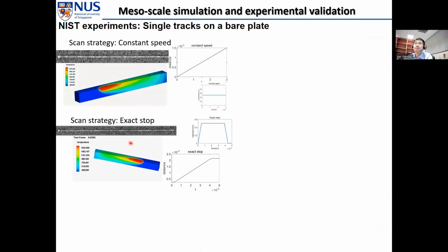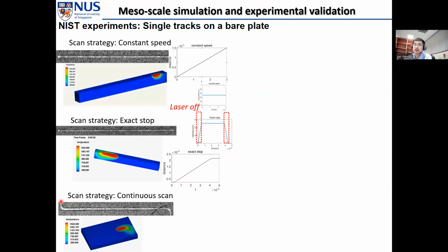So to scan a single track, there are actually different scan strategies. One scan strategy is called constant speed, which means we turn on the laser and the laser scanning at the same time. But the laser scanning is controlled by a galvo mirror, and it's a mechanical system, so there has to be acceleration and deceleration stages. So in these acceleration and deceleration stages, the energy density will be different from the constant speed stage. So another strategy is called exact stop, where we just turn off the laser during the acceleration and deceleration stages. Another scan strategy is called continuous scan, where we just change the laser scan direction in the beginning and ending.